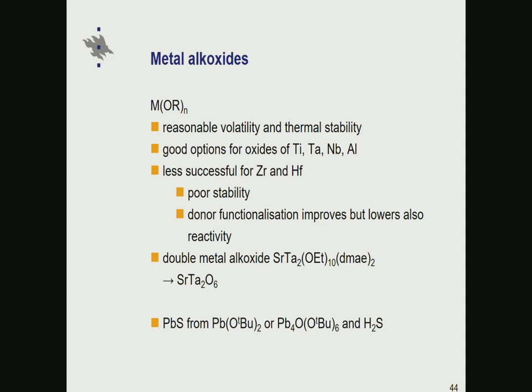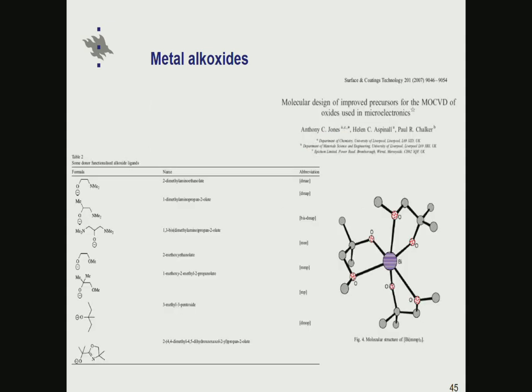We also studied quite a lot of alkoxides for zirconium and hafnium earlier. They are poorly stable, but with donor functionalization this stability can be improved, but at the same time the reactivity goes down. There are also some works about using double metal alkoxides for depositing these materials, and one can use lead alkoxides at least for sulfides as well. With these donor functionalized alkoxides, I was already showing the example with tantalum, besides having the alkoxide functionality, there are one or several other donors in the molecule as well, and as a result one can increase the coordination number and in that way improve the stability and volatility.